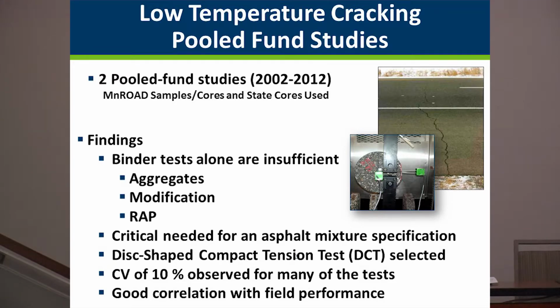Some of the findings are very significant, and I think this is where polymer modification really showed that if you added polymer modification, you got a lot better fracture energy. It really helped things. It also depended upon the aggregates that were there. We had a limestone and a granite. The granite performed much better than the limestone. And RAP, of course, didn't help as much as you'd hope. But it really showed the critical need for the asphalt mixture specification.